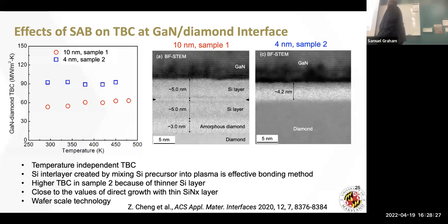All right, and so this again just shows you that I can now play around with single crystal diamond, I can play around with other materials where I can't grow single crystal on the backside, but I can bond it. And so this is moving the needle towards starting to dissipate this heat, spread the heat out at the chip level before I ever worry about liquid cooling, air cooling. I'm trying to do it right inside of the device. So we've been very lucky in terms of working with people that actually grow wide bandgap semiconductors, and they let us get inside and play with architecture to try to change the dynamics of the heat transfer inside of the devices.